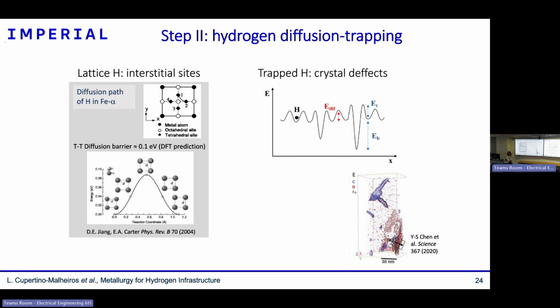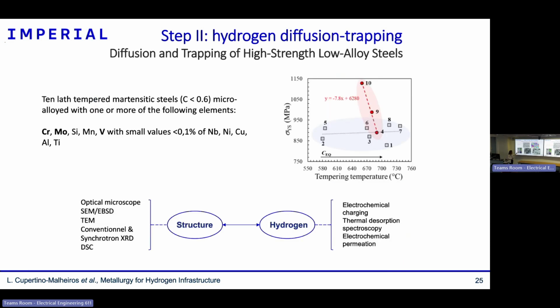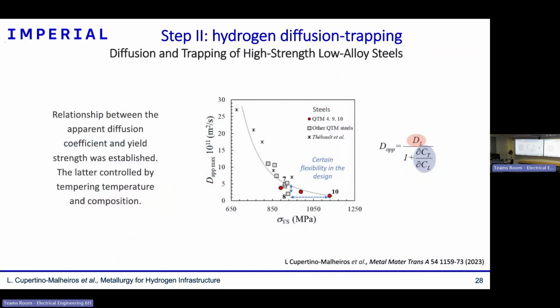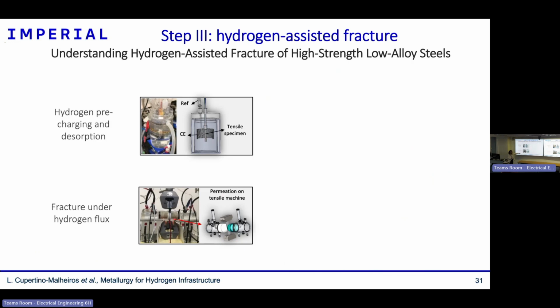Yeah. So when you do the embrittlement experiments, there are two, right? One is with a fixed amount of hydrogen, another one with hydrogen flux, which is a kind of continuous hydrogen absorption during your tensile testing? Yeah. So in the other one, no, because it was pre-charged, so it was not in the environment when I tested. This type of test here, and also the later one, the metal is still in contact with the environment, so hydrogen is still in. So in this test specifically, I first did the pre-measure. I let the hydrogen flux become stable first, and then the tensile test was initiated, so there was already a stable flux of hydrogen inside.